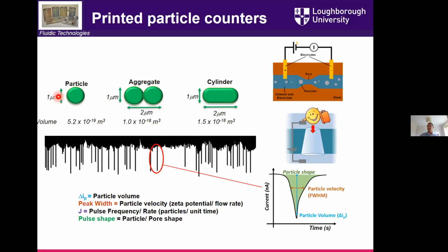So if you take droplets that have a specific feature, or there are aggregates of those, you would see twice the volume. Okay, you wouldn't measure 2 microns in terms of the total size of the droplets. You would measure twice their volume. And of course, a cylinder of comparable features has a different volume. So in theory, you can resolve all of these out by this technique. And so you can tell about concentrations, you can tell about sizes.